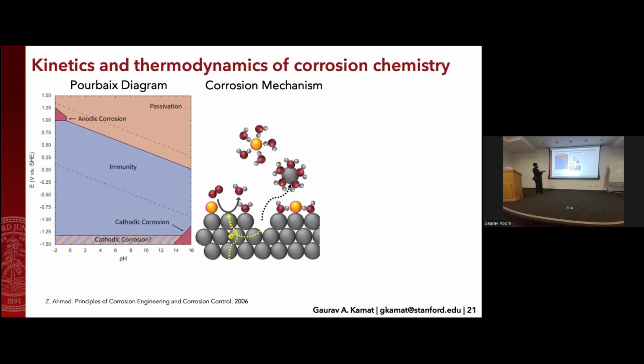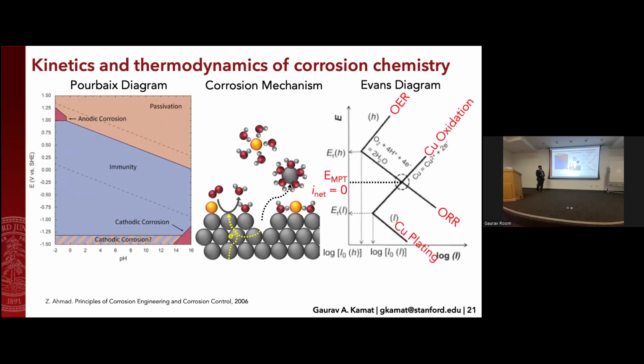So a metal atom will become a metal cation, but it can't just do this by itself. It needs to put those electrons somewhere, and it has to have a driving force to do that. Typically what happens in a lot of systems is you have surface reactions that can accept some of those electrons. So as this metal oxidizes, it'll feed electrons into a surface reaction. Now, if we connect this system to an external circuit, we can also push or pull electrons based on what potential we apply to the surface. So we can encourage or discourage this dissolution process based on how we apply the potential.